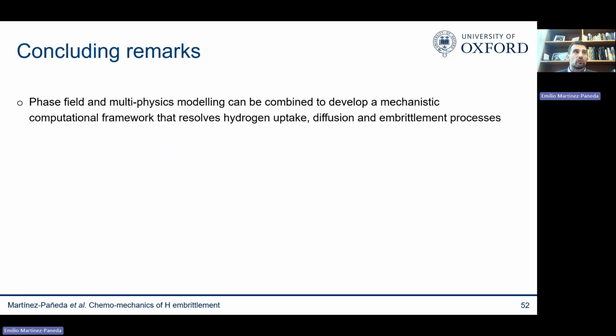So just to finish, just on time, I would say that I think the combination of phase field and multiphysics modeling, or electrochemomechanical modeling, allows us to develop a mechanistic framework that allows us to directly simulate the underlying physical processes in hydrogen uptake, diffusion, and embrittlement, and therefore that allows us to eliminate those fitting coefficients and deliver predictions that are based purely on physical properties.